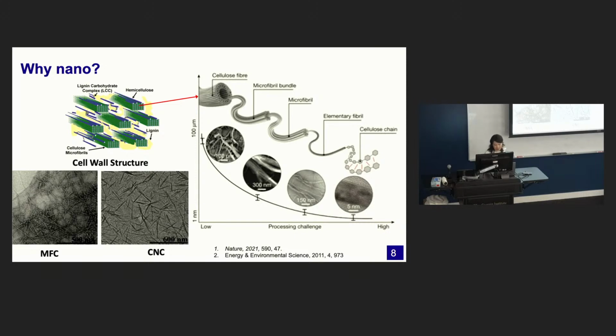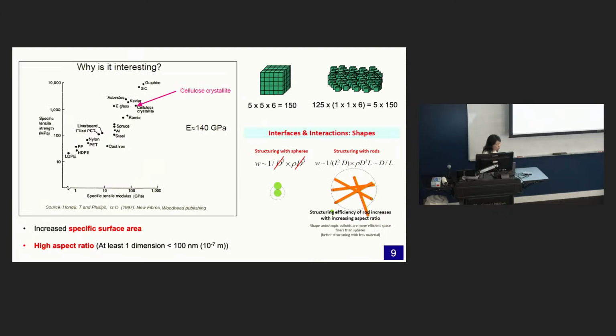So you can get nanocrystal cellulose. So as we say, why nano? If you look at this figure, published in 1997, people found that cellulose crystals have a high specific tensile strength, about 140 gigapascal. So it is even close to E-glass and much higher than steel. And also, another beauty of nanocellulose is that, except for high specific surface area, they also have a high aspect ratio.